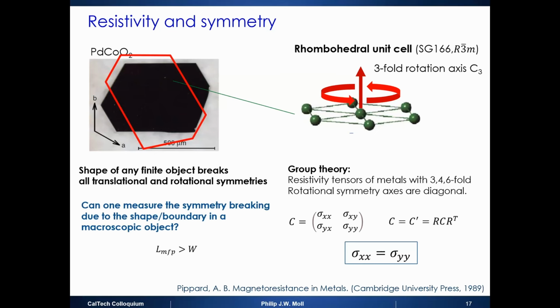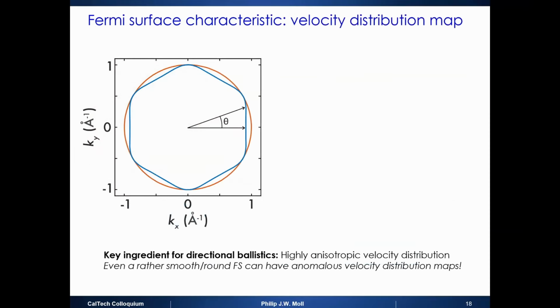And that's actually somewhat of a non-trivial statement, because you can have a crazy Fermi surface that obeys the right point group symmetry. And it will always give you, from a Boltzmann point of view, an isotropic in-plane transport. So you never see anything about the shape. But if you make it small enough, you actually do. And that has something to do with the way that the Fermi momenta and the Fermi velocities are distributed. So here I compare the real Fermi surface of palladium cobaltate to a circle, right?